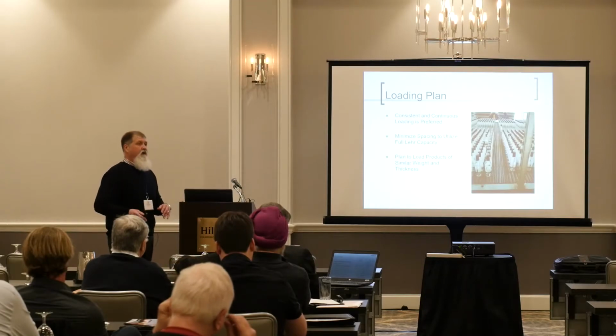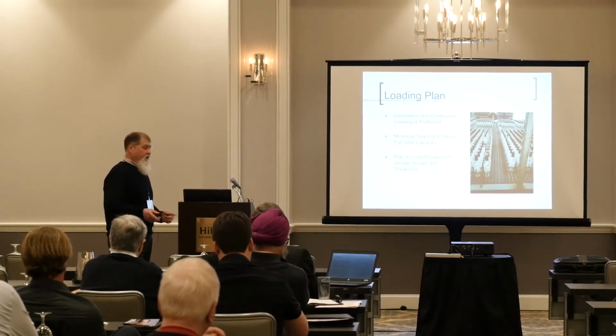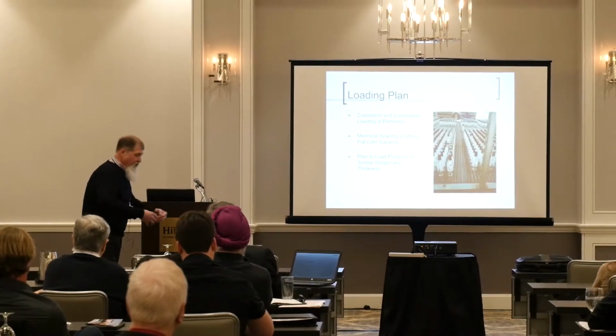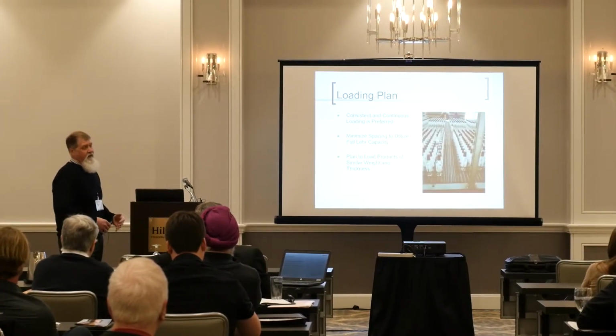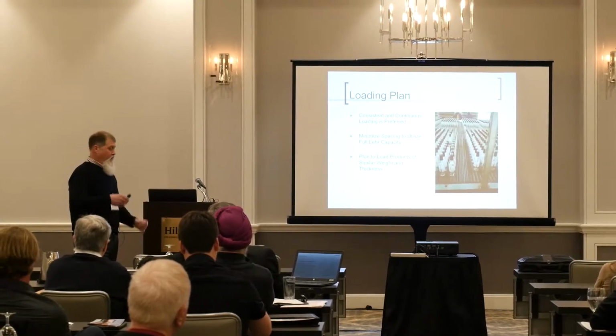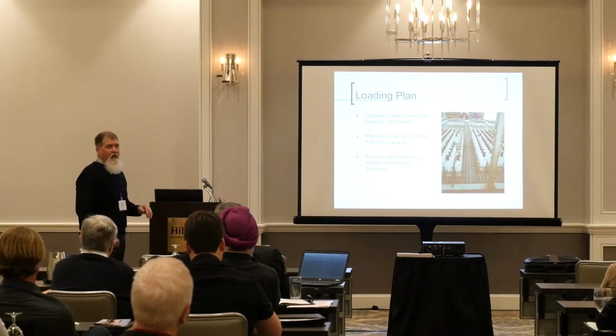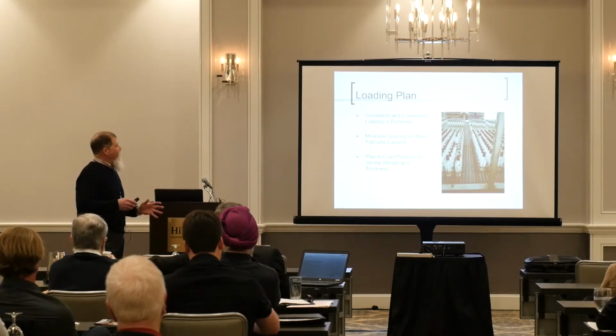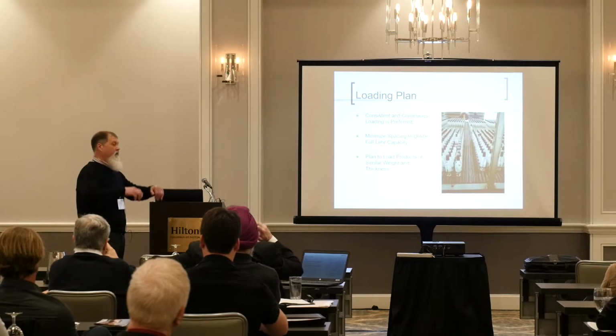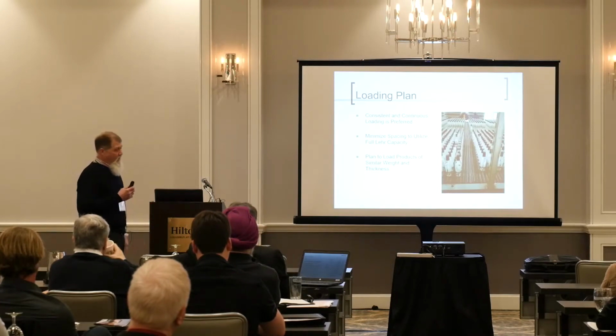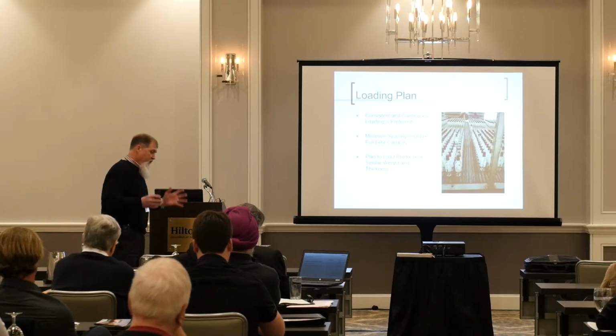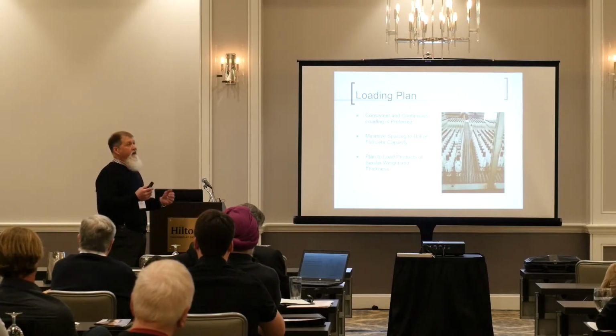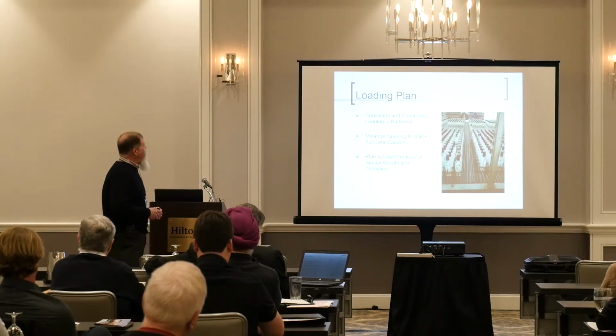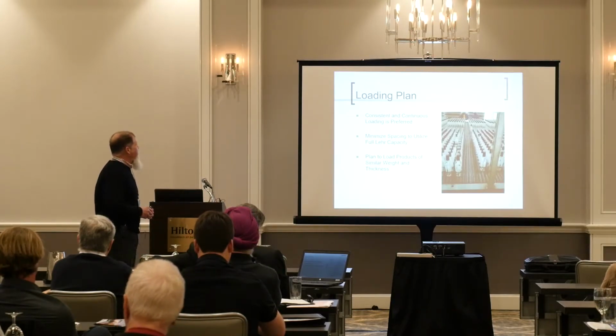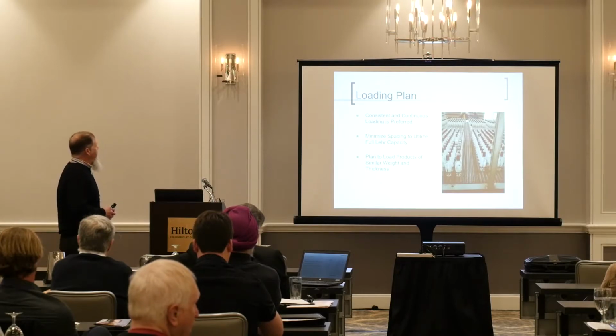So, you've got a constant load moving through there and everything's great. The lehr empties out and then you start and load another group of ware. The first half hour of the product gets overfired and you slump the stems on your wine glasses or whatever. That's due to the lehr emptying out. Whatever heat source you're using, if it's elements or gas-fired burners, they're going to fire up trying to maintain the temperature, and that can create some problems. So again, the loading plan definitely is a part of maintaining a consistent fire.